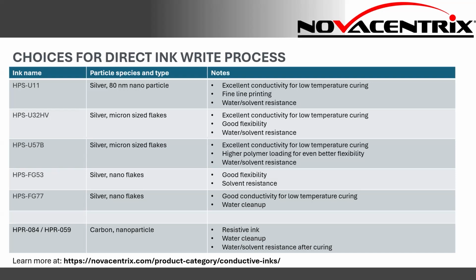The 32 HV has very good flexibility, and the 57B, which we would actually really recommend for printing directly on fabric, because of its higher polymer loading, actually has even higher flexibility. Both of these, after they're cured, are water and solvent resistant. So that really makes them a very good choice for use in lab scale. But besides that, the other two inks that I talked previously about, the FG53 and FG77, still continue to be very good choices. They both have good flexibility and good conductivity at low temperature curing.